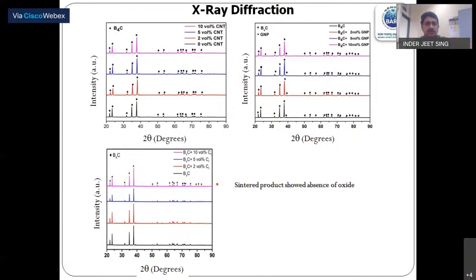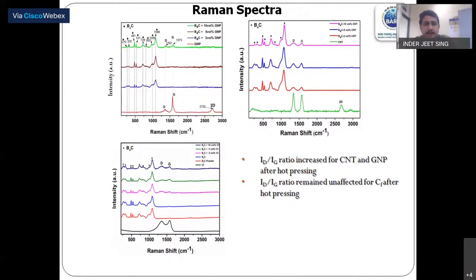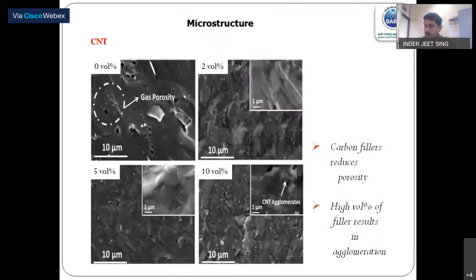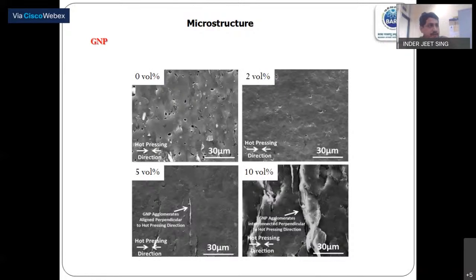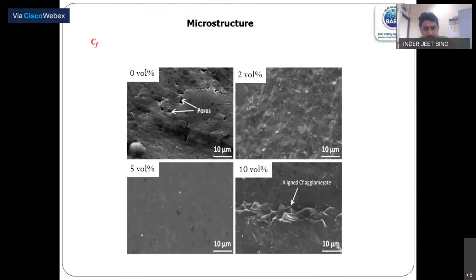This is the X-ray diffraction showing there is no oxide phase, which generally comes into the boron carbide, but here it shows the absence of oxide in the XRD. And the Raman spectra shows the presence of both boron carbide as well as the carbon nanomaterials. Now I'm coming to the microstructure part. When carbon nanotube is added with increasing volume percentage, you can see a reduction in the porosity. But after a certain volume percent, once again we see agglomeration. So that means a very high volume percent is not required. The same thing happens with graphene nanoparticle as well as the carbon fiber.